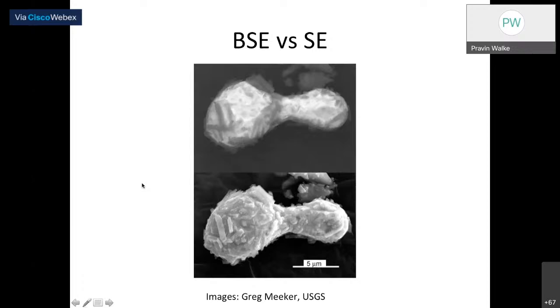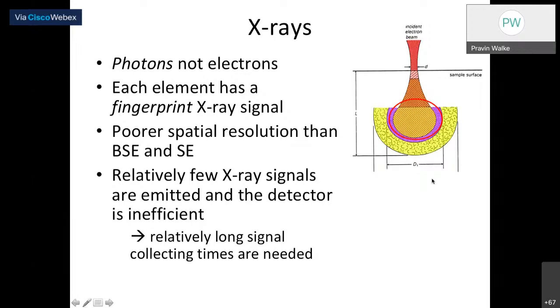So here you see the clear difference between the BSE image, the upper image from the backscattered electron detector, and the image processed by the secondary electrons, right? You can clearly identify the difference between the images. The SE image is giving more information, very high depth and a very clean image using the SEM. But the BSE image is not so clear, and the contrast is not very good, right? So that's why SE is highly preferred for SEM imaging.